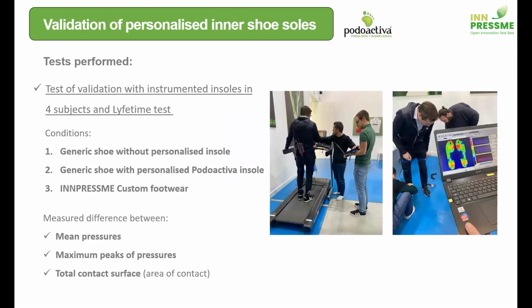For the tests, in these 4 different patients, they compared the generic shoe that you get in the shops, this generic shoe with the personalized Podoactiva insole, and also the custom footwear that we developed in the project. They measured mean pressures, maximum peaks of pressure, and the total contact surface area. The generic shoes off the shelf gave the worst results. The personalized Podoactiva insole gives slightly better results, and the custom footwear with INN-PRESSME gives slightly better results than the second case.